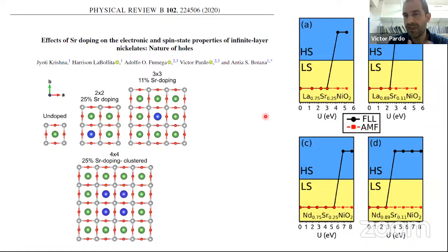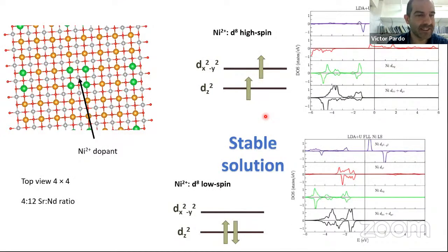And if they are low spin, that makes these nickelates closer to the cuprates when doped. The cuprates, when you dope them with non-magnetic dopants. And these nickel 2+ dopants that Harold Hwang introduced to create superconductivity, calculations say that they are not magnetic. As I said, with this 4x4 supercell, where we have these 4 strontium here around this particular nickel, this is nominally a nickel 2+, and we can see how the density of states of a nickel 2+ would be in that material. And we see that the stable solution is the low spin, just like in the other supercells that we calculated. And we can look at the density of states for the different orbitals.